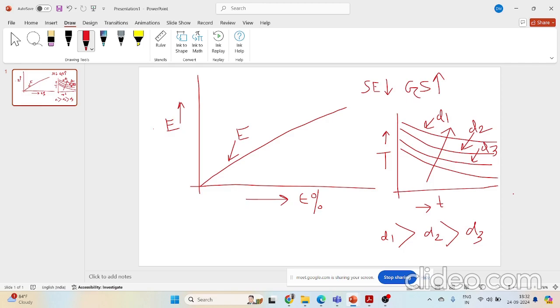So we talked about recrystallization. We talked about grain growth. Now, will there be any effect of recrystallization and grain growth in the fusion zone? In the fusion zone, you are going above your melting temperature, right? So because of melting, the work hardening will be completely gone. And in the heat affected zone, it will be partially lost because of recrystallization and grain growth. So these strength losses should be taken into account when you design your weld joint, right? Those things need to be taken into consideration during your design of the weld joint.